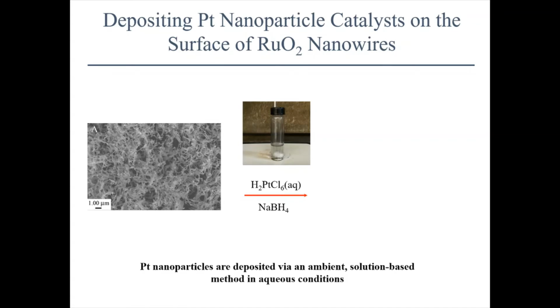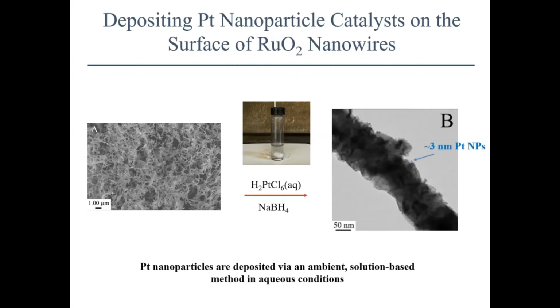So once we did our template-based synthesis and our characterization, we knew that we had our catalyst support. But the next step is to develop an active catalyst by taking your support and depositing platinum nanoparticles on the surface. We use a fairly traditional technique, an ambient solution-based method in aqueous conditions, where we took platinic acid, dissolved it in water, and used sodium borohydride as a reducing agent to convert the platinic acid into platinum, and it formed these nice uniform 3 nanometer particles well dispersed over the surface of the ruthenium oxide. We also did the same exact protocol on Vulcan carbon as a control, which is the traditional catalyst support, and we got a very similar catalyst distribution and catalyst size.